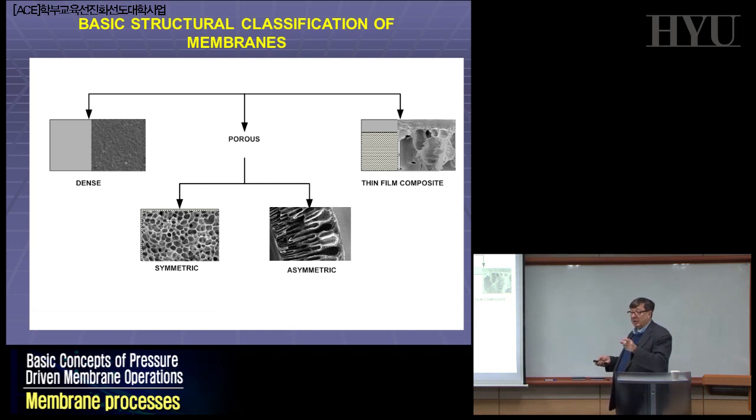So all this story you have to learn in liquid phase, but the same story is in gas phase, to realize an asymmetric structure in which you have a material, a film that you can handle in your hands. But in this material, most of it is porous, and only 1%, 0.1% is dense, and that means it's controlling, it is selective, basically. Okay? This can be realized in different ways, and you can have what we call thin film composite.